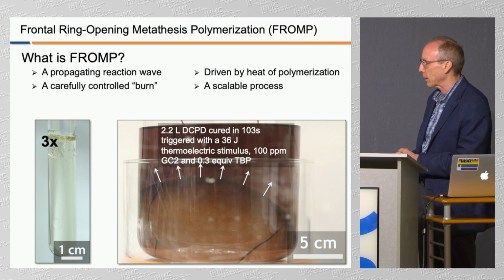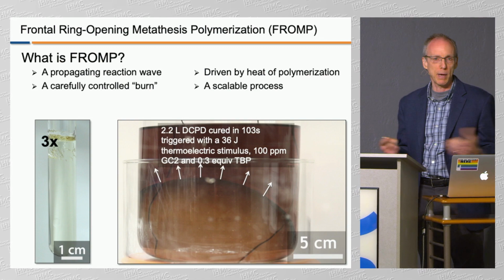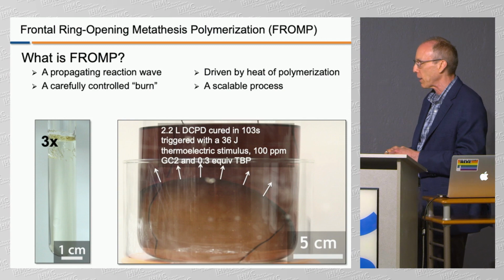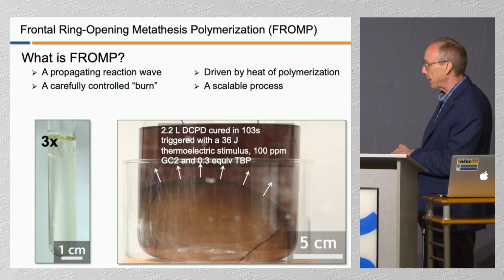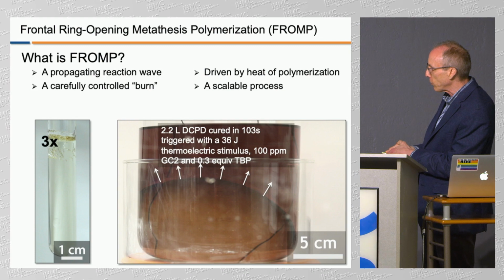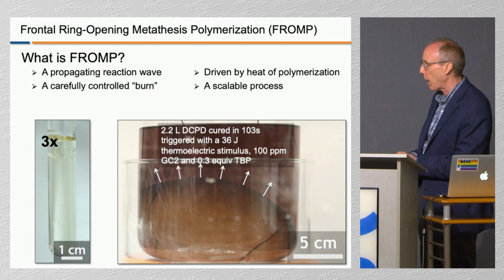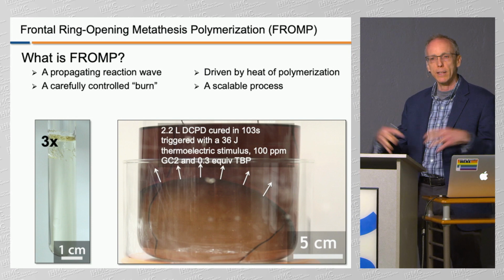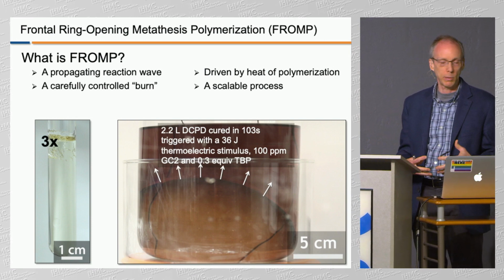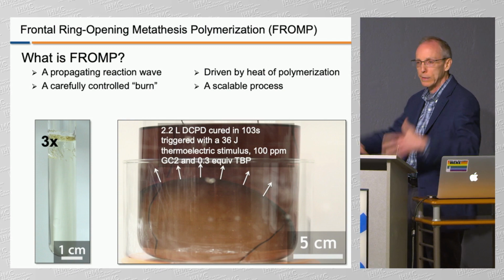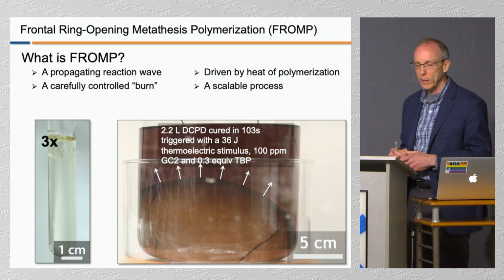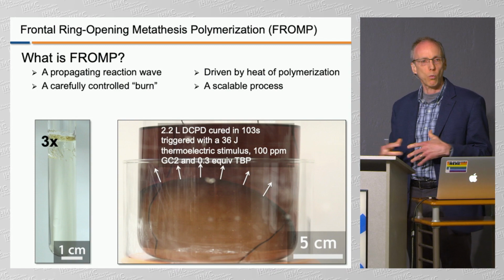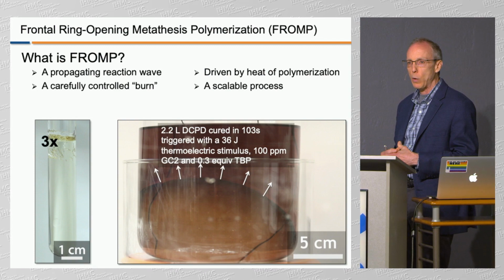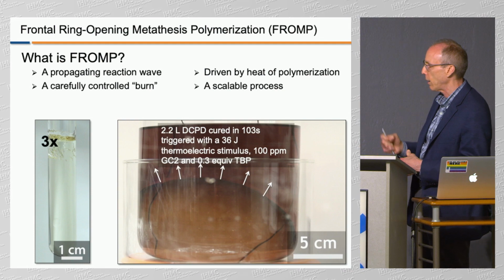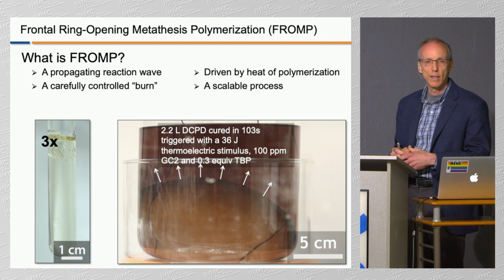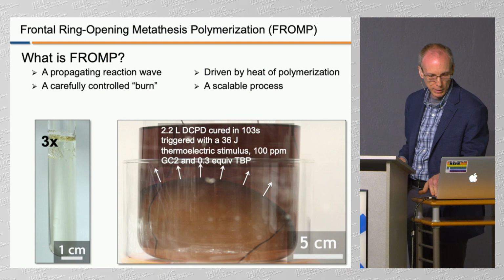GC2 is really important. It's the Grubbs Catalyst 2. Grubbs was my postdoctoral advisor, and I learned about metathesis polymerization from him and his group. And then there's this magic thing that we added, which I'll tell you about, because if you mix the catalyst with this raw material, the monomer, you would expect that it would take off right away. We wanted to be able to stabilize it as this water-viscous liquid that we could move around and manufacture, but then spark it with a little bit of heat to basically cause this reaction to take place.